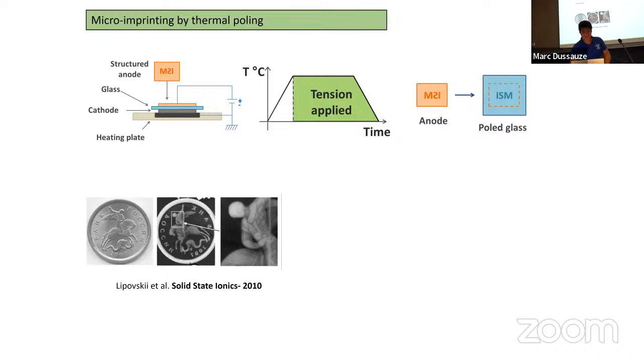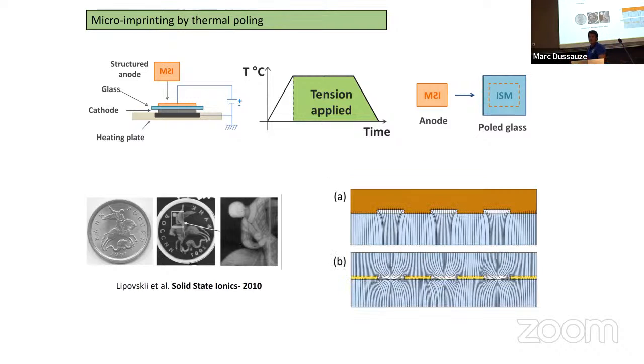The second point, which is very interesting, is that this kind of process can be developed as an imprinting process. So if you don't use a classical homogeneous electrode, but if you use an electrode which is patterned, then you can transfer the pattern to the glass surface. The very nice example here is the work from Lipovsky, who has transferred the coin inside the glass surface. Very easy. In this case, the second thing which is very important is that you will have the opportunity to play with the field geometry. So you will be able to choose the electrode in order to select the different geometry of your electric field applied to the glass surface. So these are two examples, one where the electrode is just a change of topology, and this one where the electrode is a juxtaposition of different conductive and non-conductive areas.